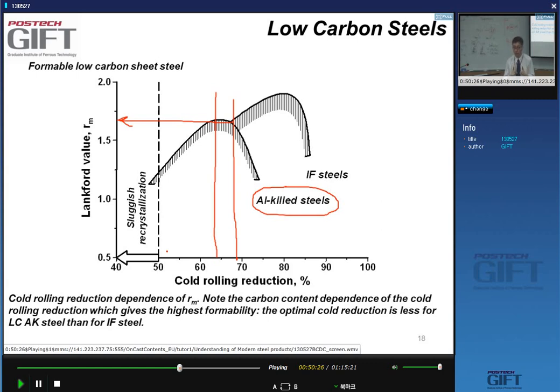Yes? Okay? So that means if you want a final product, your starting hot strip must be within a certain range, right? You don't have so much playing ground, yes? This is also one of the reasons for the advantages of IF steels, yes, you have a much larger range over which you can deform the material, right? And in particular, you can give very large reductions.